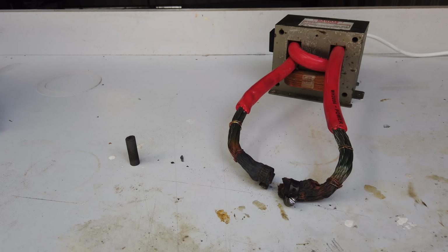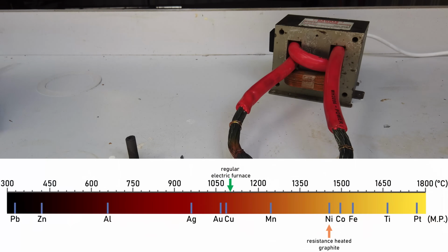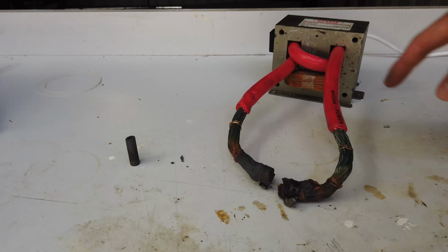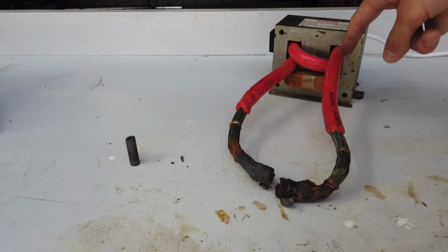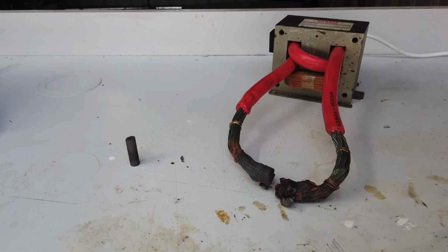Whilst being slightly disappointing, this does narrow down the temperatures that we can reach with a setup like this. So seeing as we were able to melt nickel but not titanium, we must be able to reach temperatures within this range. I reckon if we could get one more turn of the secondary winding here, that would more than double the power that we're putting through an equivalent resistance. So no doubt that would be nice, and we would probably then be able to melt the titanium.